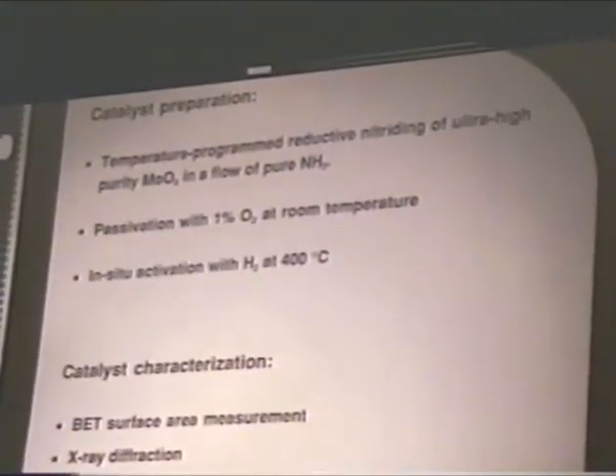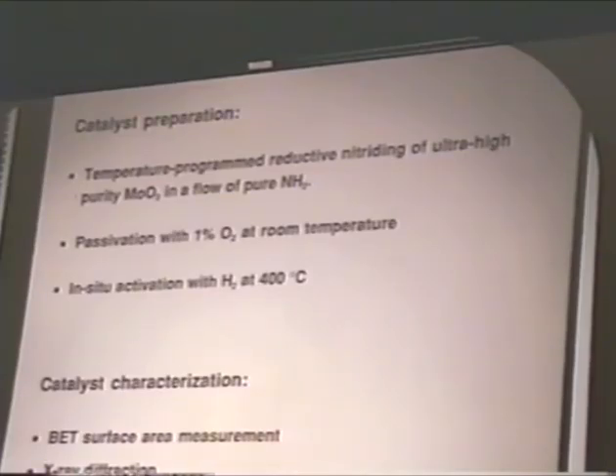Catalysts in this study, the nitride catalysts, have been prepared using a temperature-programmed reductive nitriding process of ultra-high purity molybdenum trioxide in a flow of pure ammonia. This is a fairly involved process which includes several ramping and cooling stages, followed by a passivation step with oxygen at room temperature. This is usually done over a period of 24 hours. And then in situ activation with hydrogen at 400 degrees centigrade for about 12 hours. The catalyst characterization techniques that we have used include BET surface area measurements, X-ray diffraction, TPD and TPR experiments, scanning electron microscopy, and especially for the post-reaction characterization, controlled atmosphere X-ray photoelectron spectroscopy.